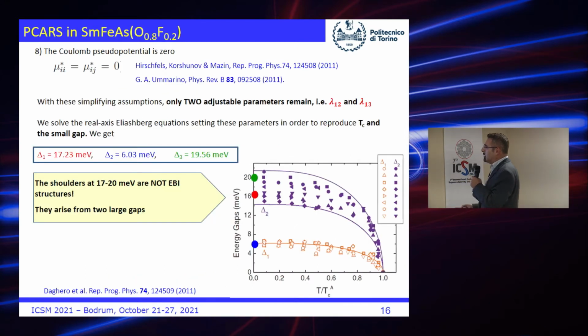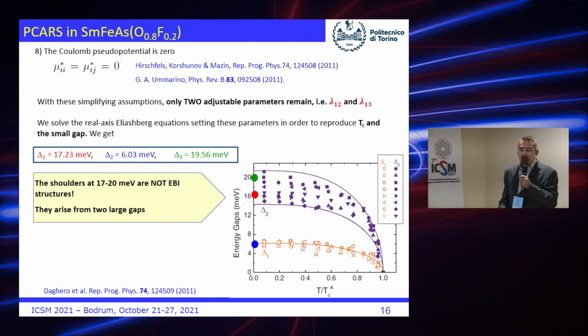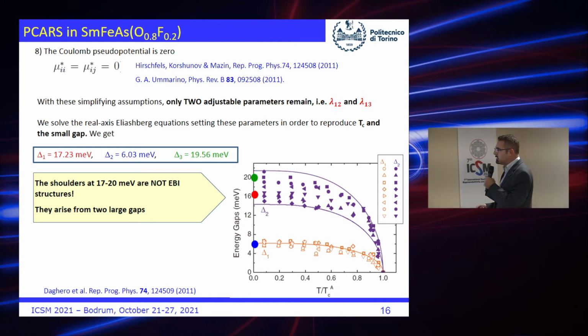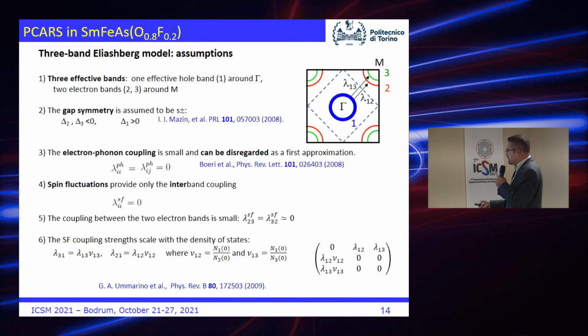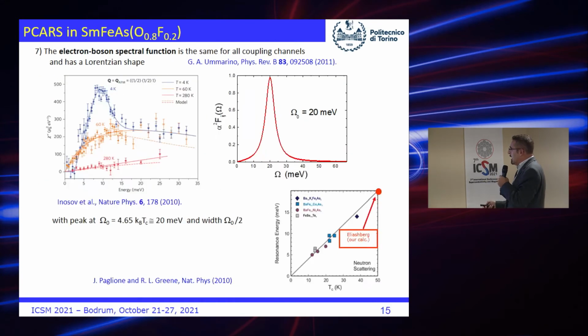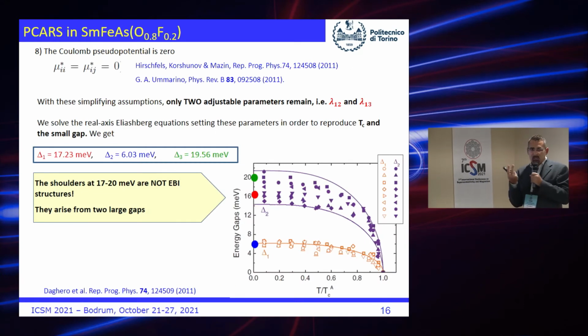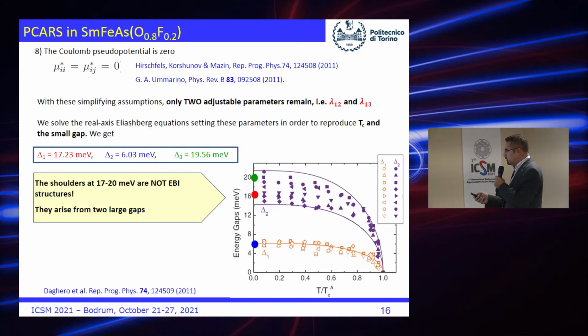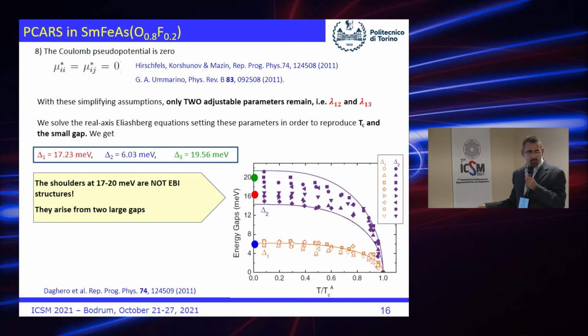Then the Coulomb pseudopotential. Well, the Coulomb pseudopotential is always difficult to handle. Nobody knows exactly how to calculate it. We know that it is small in these compounds, and for the time being we'll fix it to 0 as well. So in the end we have only two parameters, lambda 1,2 and lambda 1,3. That means these two, okay? And with these two values we can fit two things. We chose to fit the Tc and the small gap, which is the one we know better, okay?